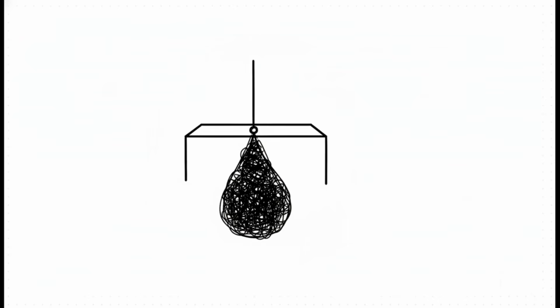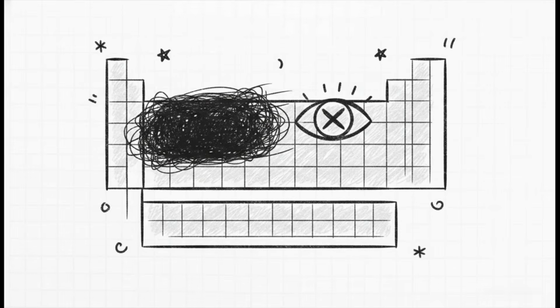However, when those electrons hit the sample, they don't just stop at the surface. They scatter downward and outward, creating this teardrop-shaped interaction volume that can plunge hundreds of nanometers deep into the material. So while your beam is aimed at a tiny 20-nanometer particle, the X-rays bouncing back to the detector might actually be coming from the thick substrate underneath the particle. You might get a huge signal for a material that isn't in your nanoparticle at all, but is actually just buried beneath it.